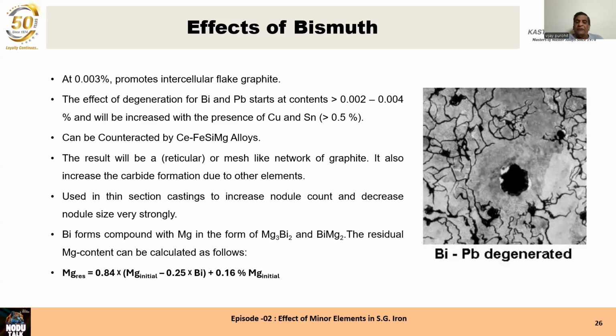Fortunately, their effects can be neutralized. Bismuth effect can be neutralized with the addition of cerium. So you have to use rare earth containing ferrosilicon magnesium treatment alloy. The result will be a reticular or a mesh-like network of graphite. It also increases the carbide formation due to other elements present along with the bismuth, used in thin section castings to increase the nodule count. Bismuth is very effective in increasing the nodule count and decreasing the nodule size very strongly in thin sections.